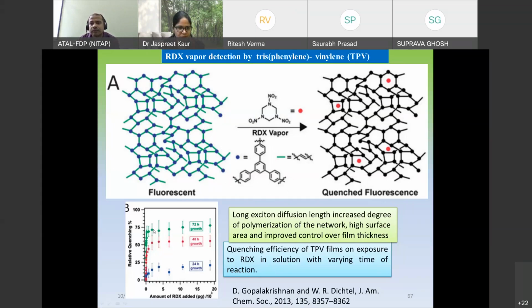So you can see it shows better quenching efficiency even in the films obtained from these TPV molecules. They show better efficiency for the RDX molecules. Even this Dichtel group also studied the growth rate of the films for the quenching efficiency of the TPV films. At 24-hour growth, they show better detection relative quenching. You can see it is approximately 75% after 72 hours of growth, and at 24 hours it was